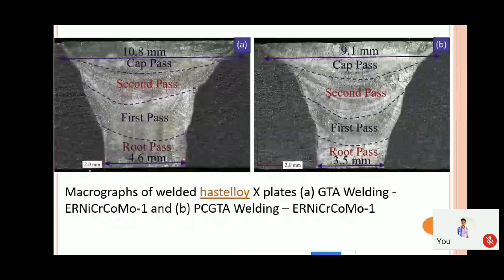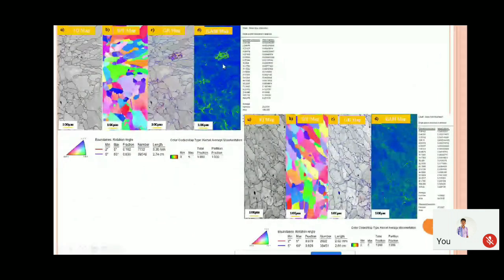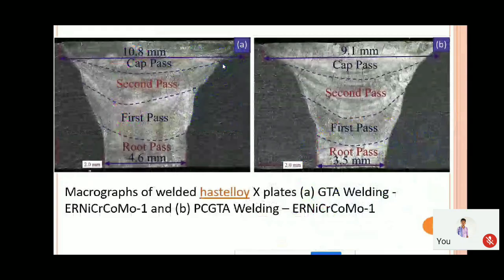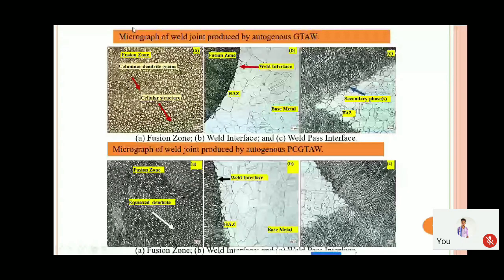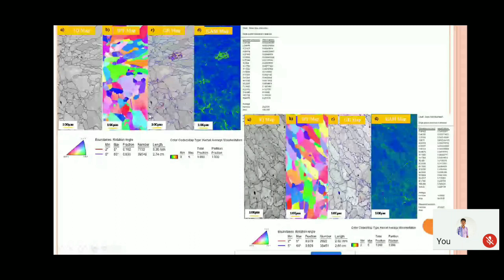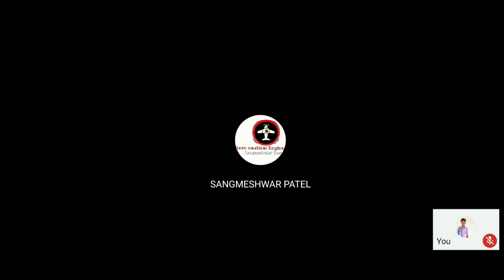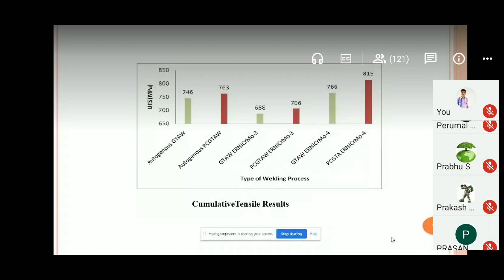And yeah, this is another one. This is the EBSD analysis. We have carried out the electron backscattered diffraction image, EBSD, to measure the grain sizes. As I told you in the previous slide, the grains over here compared to here are very fine, right? So in order to understand the size of the grains, as compared to GTA and PCGTA, we did the analysis for both GTA as well as the PCGTA welding process. Here we can understand that the grains are completely refined. You can see here the grains are coarser in the GTA case, and in the PCGTA case the grains are very fine.